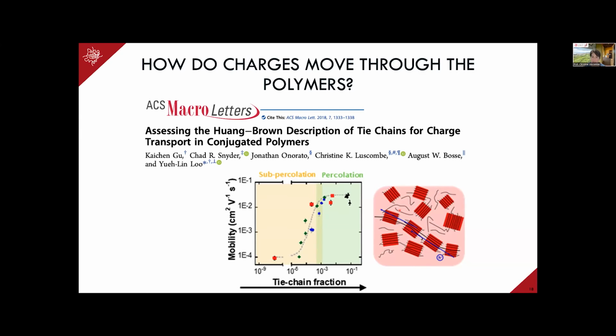And we generally know that the macroscopic film, and the question was, well, how do the charges move from crystal to crystal to reach the other end of the film? And what we were able to show in this particular paper was that you do actually need tie chains connecting these crystals. And by having access to well-defined molecular weight systems, we were able to alter the tie chain fraction, and were able to determine what tie chain fraction was really needed in order to get good charge mobility coming through the material. So this is just one example of a collaboration that we were able to do by having access to well-defined systems.